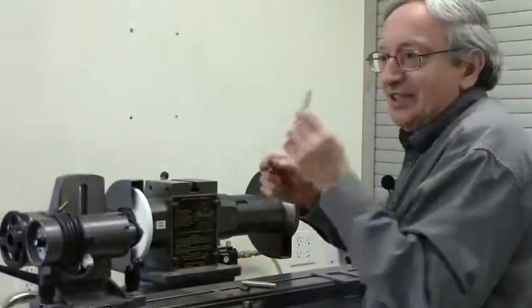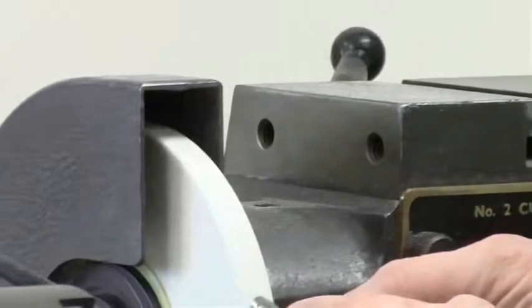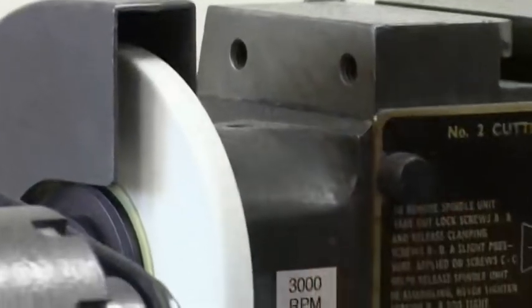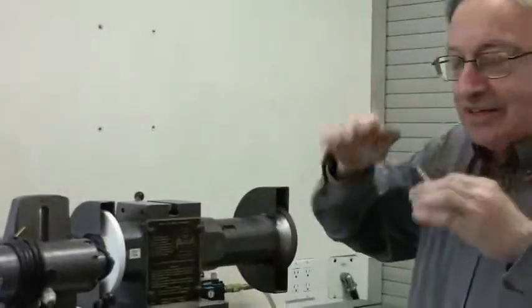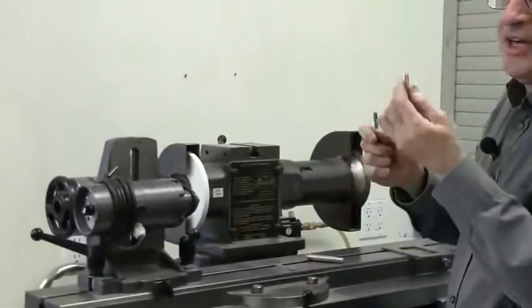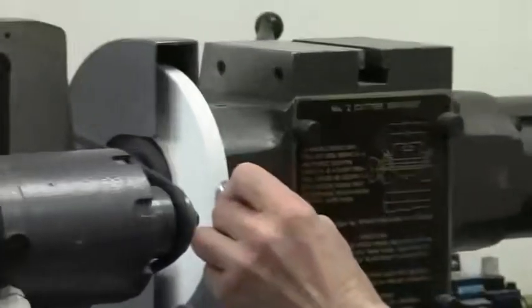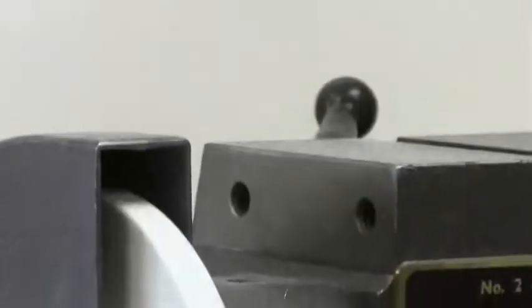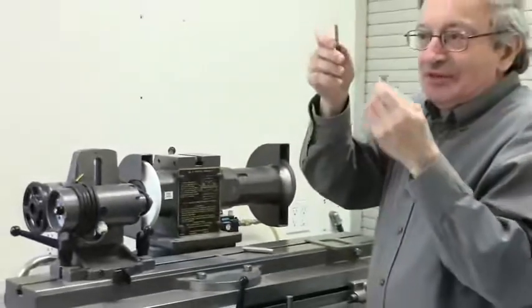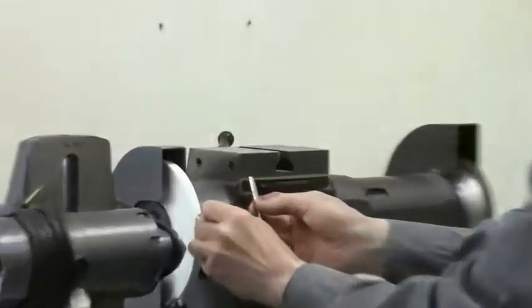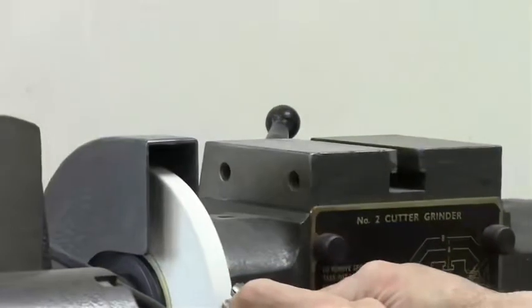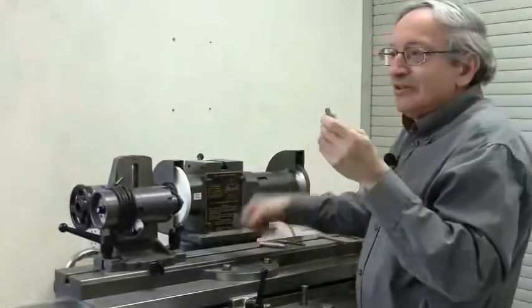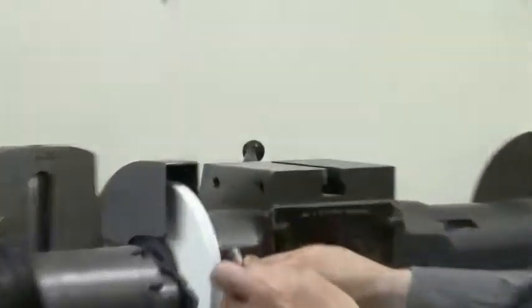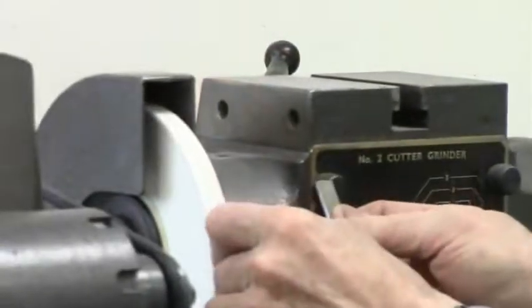Now, a high-speed steel has even darker sparks, almost no sparks at all, practically no sparks at all, and the few sparks are very dark, like redder rather than white. And the surgical stainless, the 440, again, no sparks at all. So basically, it's hard to tell the high-speed steel from the surgical stainless, but still the high-speed steel sparks just a little bit more. But it's very easy to tell the surgical stainless from the regular A2, because the regular A2 looks like this, and the surgical looks like this.